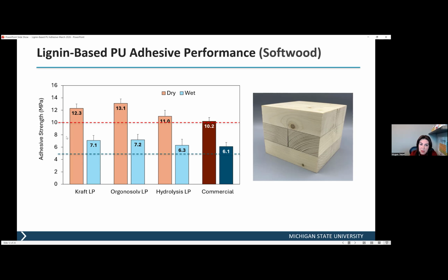Based on the requirement, the dry adhesion should be above 10 megapascals. And then the wet should be above 5 megapascals. And you can see that all the lignin-based adhesives met the standard requirement, and they're actually outperforming the commercial adhesive.